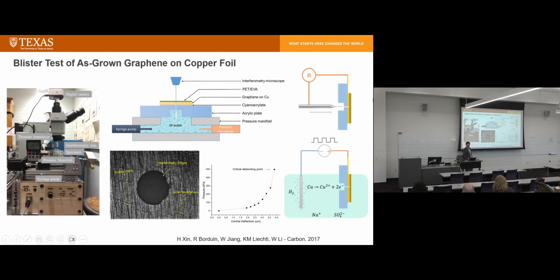And then this is the backing plate, a polymer backing plate. You have to have this to make sure the sample is not deformed due to the big pressure over here. And then after drilling a hole, we use an electro polishing method to remove the copper. We generate the hole to reach the graphene surface.